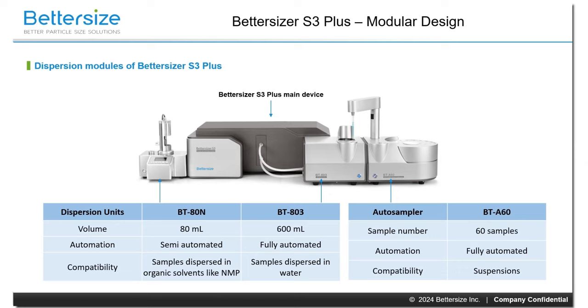To help better utilize the unique design of the Bettersizer S3+, making the best performance, and to do measurements more easily, we provided 2 dispersion units and 1 optional auto-sampler for it. If the particles are insoluble in water and come in a large quantity, such as some lithium iron phosphate LFP materials, then BT803 can be the most ideal choice. It is a fully automated dispersion module with automated test functions. As for samples dispersed in organic solvents, the BT80N works perfectly in this scenario. It is okay to dilute the sample with NMP in the BT80N and then do the test with the Bettersizer S3+. To make the size and shape measurement of suspensions easier, the BT-A60 auto-sampler is here to help. It can hold up to 60 samples and only 1 click is needed to do those 60 measurements.